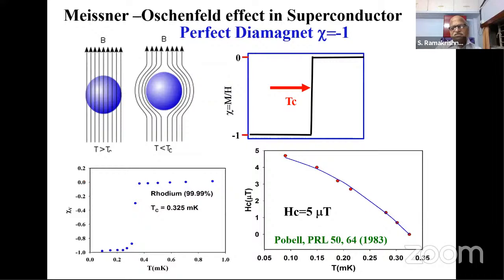As I said, one of the second fundamental properties of a superconductor is that it acts like a diamagnet. When you have a normal metal above its transition temperature, the field penetrates. When you cool it, it expels the magnetic flux. Inside, the field is zero. So when you measure the susceptibility as a function of temperature, what you see is a kick like this. The diamagnetic susceptibility is very, very small, and then you see a huge diamagnetic susceptibility, almost -1. So this is what the TC is all about. If you do a magnetization experiment and it is a superconductor, you will get a signal like this.